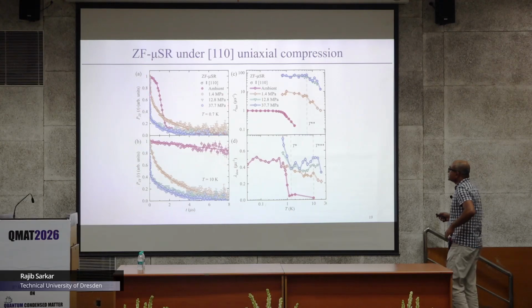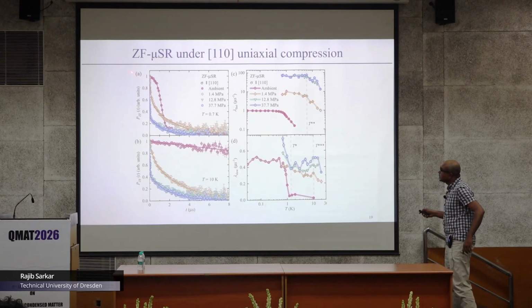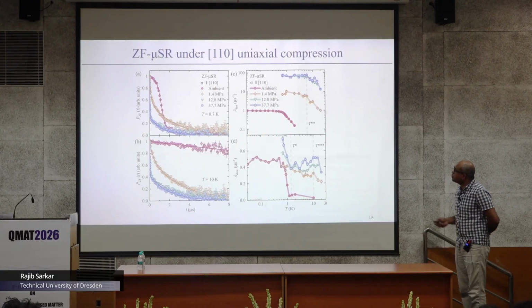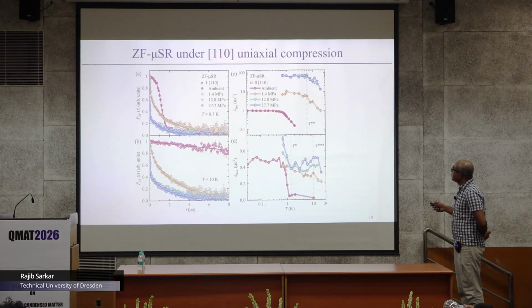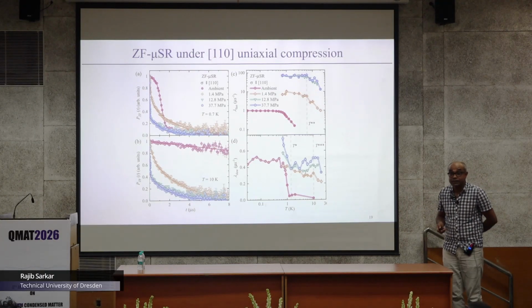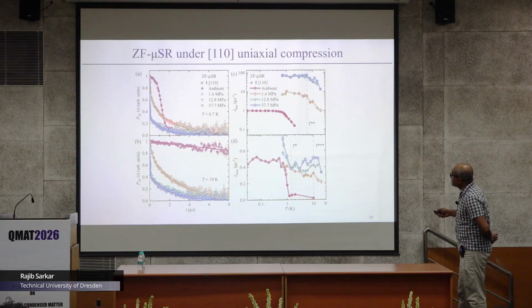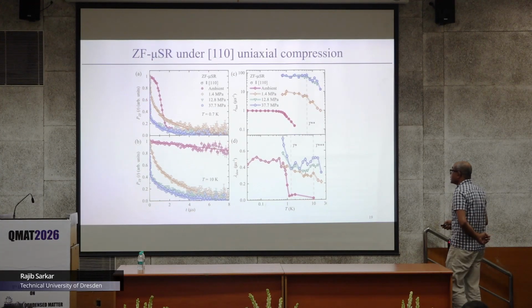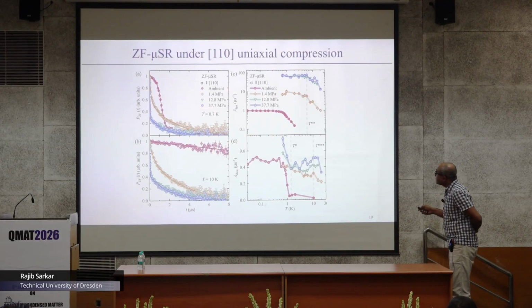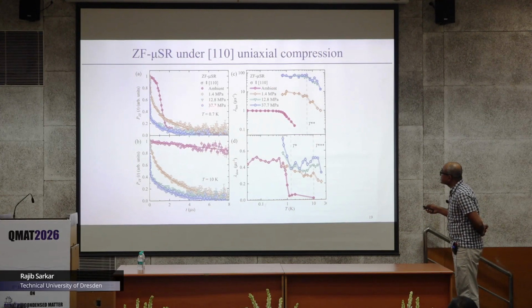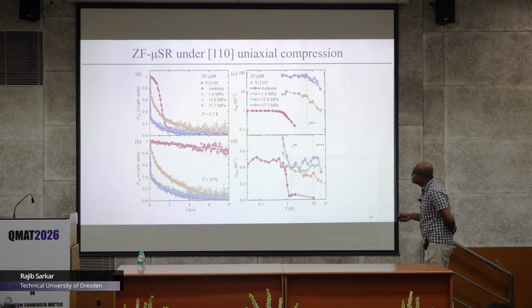So this is the plot. In plot A, the left panel shows a zero field muon spin rotation spectrum under uniaxial compression or stress in the 110 direction. This is the time axis, and this is the y-axis, which is your polarization or the asymmetry. We have applied pressure up to 37.7 megapascal, starting from ambient pressure. So this is the ambient pressure data, the filled magenta circles.